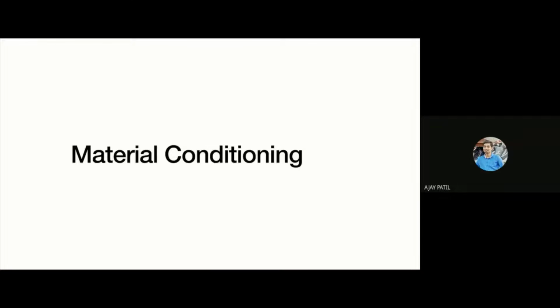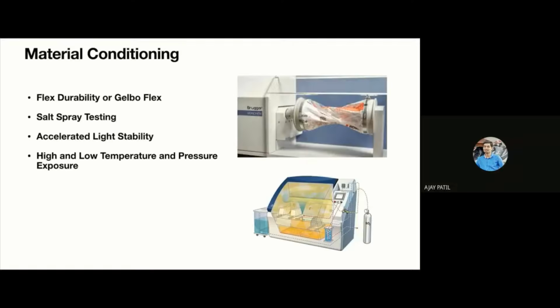To give you an example, when you have a structure which has an AlOx layer or a metallized layer inside it, now an AlOx layer is very sensitive and has very low flexural strength. So if we subject it to a Gelbo Flex movement, then the results would be very different before and after if we do a comparison of the barrier properties. So such kind of applications in combination can help us get very interesting results.